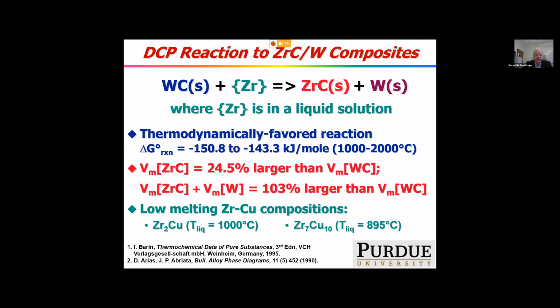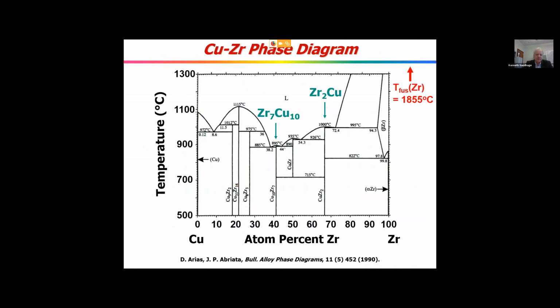Now, we don't usually use pure zirconium as the liquid because of its high melting point. Instead, we alloy the zirconium with a solvent, copper, which substantially lowers the melting point. In the case of Zr2Cu, a congruently melting intermetallic, down to 1,000 degrees C, which is a much more manageable temperature for doing these reactive infiltration experiments. And to show you what I mean, here's the copper-zirconium phase diagram. Zirconium melts around 1855 C. If you add just a third copper, you can form the Zr2Cu congruently melting intermetallic at 1,000 degrees C, which from a furnace technology standpoint is a much more manageable temperature than 1855 C.